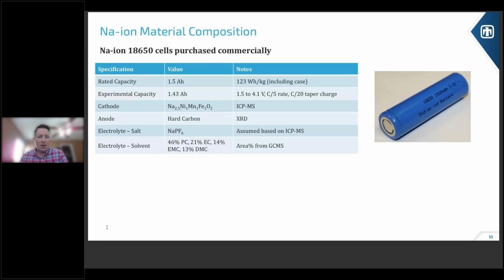We did some materials characterization. So we took the can apart, took all the materials out, did characterization. We found this to be the layered metal oxide variety. So if you recall from Ramesh's slide, there's a layered metal oxide, there's a Prussian blue, and there's a polyanion version of current cathodes for these cells. This is the layered metal oxide iteration. As he also mentioned, hard carbon is pretty prevalent. These were hard carbon anode. The salt is kind of a corollary to lithium ion, which is LiPF6. In this case, it's NaPF6, or sodium. And then the solvent that you see there is a combination of typical organic solvents that you would see in a standard lithium-ion battery. So there's almost no difference in the type of solvent in this cell between sodium-ion and lithium-ion. Next.